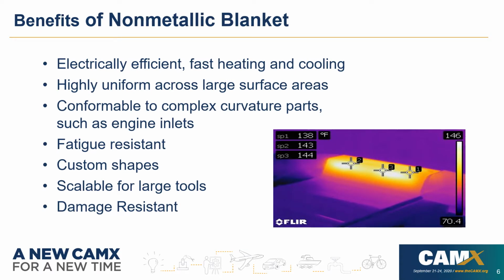Our heater blanket uses a carbon-based electrothermal film. This is a continuous film. It might be different than what you might find in the market with metallic filament blankets. This actually leads to a more energy-efficient blanket, as the whole film is heated up, as opposed to metallic filaments that really have a spacing between the elements. It's also much more conformable and drapable.